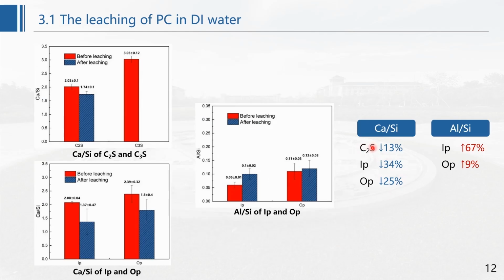We can see that after leaching, the calcium to silica ratio of C2S, inner product and outer product all decrease, while the aluminum to silica ratio of inner product and outer product increase, especially for inner product. The aluminum to silica ratio increased by 67%.